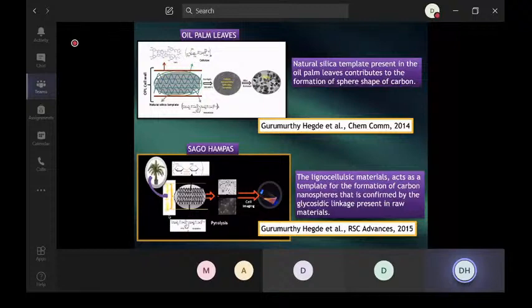So definitely there is no question of silica acting as a template for this. But here, lignocellulose material acts as a template for the formation of carbon nanospheres, which is confirmed by the glycosidic linkage, not from the earlier explanation. Here, glycosidic linkage is responsible for creating such kind of templates. So that has been proved by the zeta potential, because the zeta potential of the oil palm leaves is slightly less compared to sago hampas.